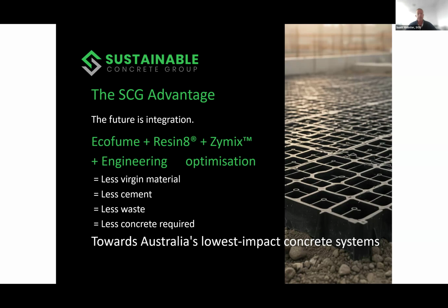As a result, if we were looking at factory floors at between 200 and 350 mil thick, depending on the need, this then eliminates the need for steel rebar being used. And if we are pouring, for example, at the upper limit, 90 mil or 100 mil of concrete in comparison to 200 mil, you can see very quickly a savings that is going to come about as a result of that.